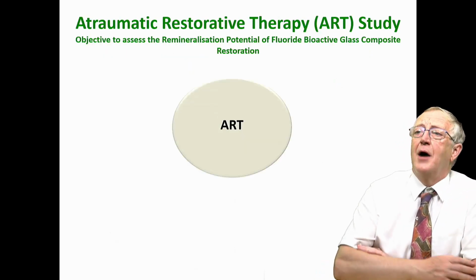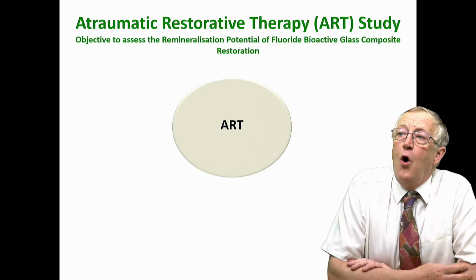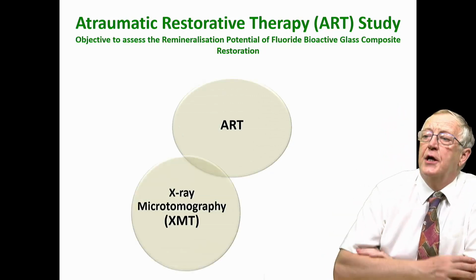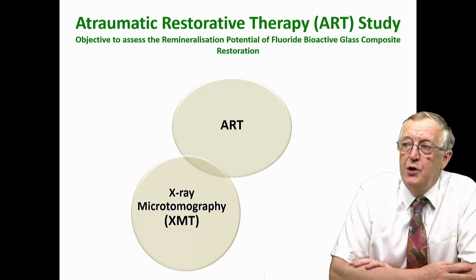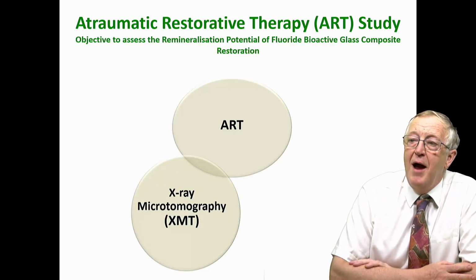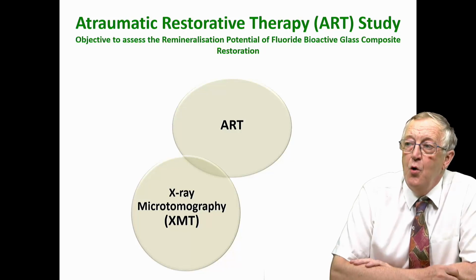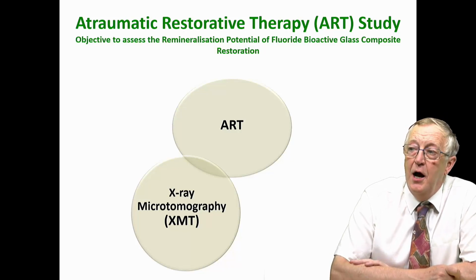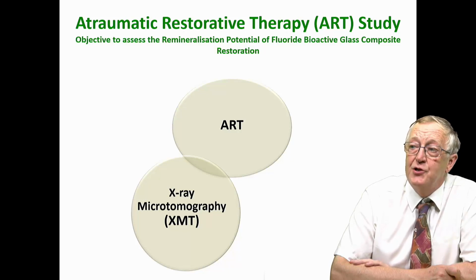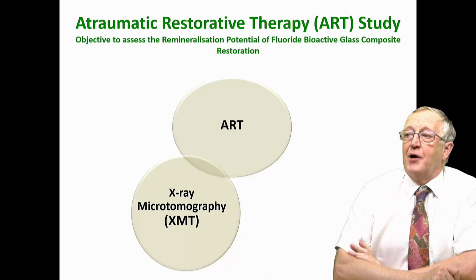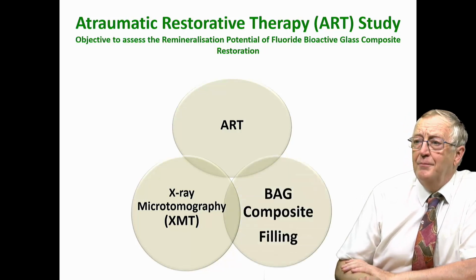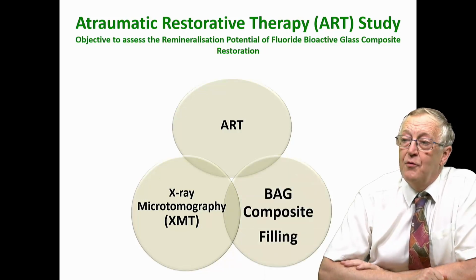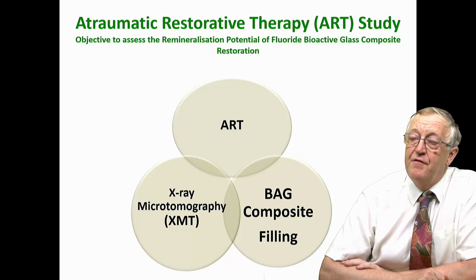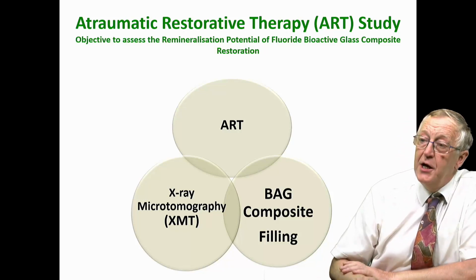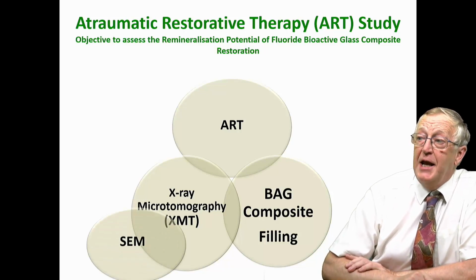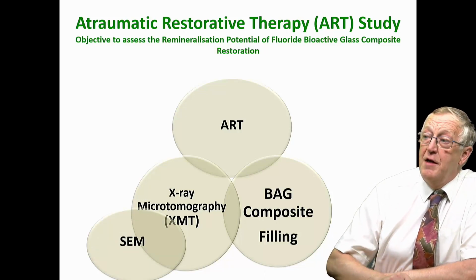We're going to talk now about atraumatic restorative therapy, or ART, and we're using ART in conjunction with a technique that we use extensively at Queen Mary called X-ray microtomography, which is a way of imaging materials and teeth in 3 dimensions at micron scale resolutions. And we're using, rather unusually, a bioactive composite filling rather than the glass ionomer cement. And at the end of the experiment, we're doing scanning electron microscopy to get some further information.